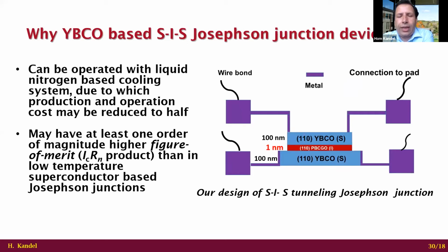Here is the design of our SIS YBCO-based Josephson junction device, where we have this extremely thin 110 PBCGO electrical insulator sandwiched between the two 110-type YBCO superconductors. The advantage of this design is that it can be operated with a liquid nitrogen-based cooling system, due to which the production and operation cost may be reduced. Likewise, it may have at least one order of magnitude higher figure of merit, the IcRn product, than conventional superconductor-based Josephson junction devices.